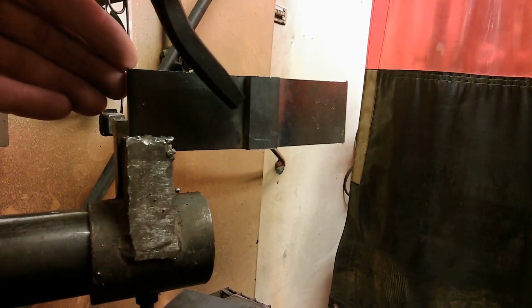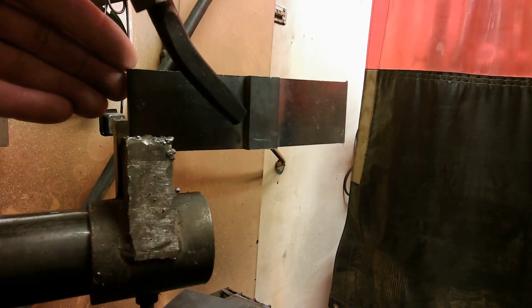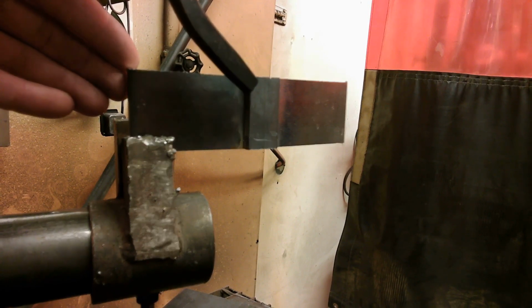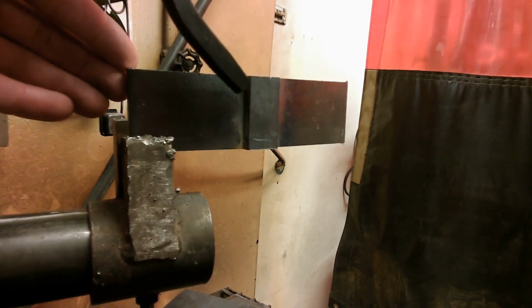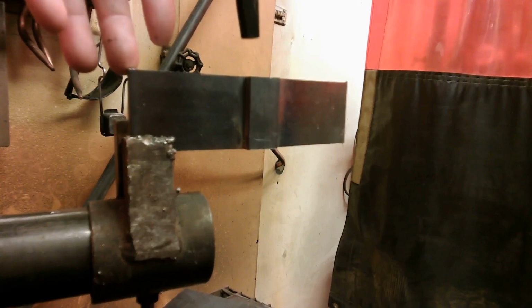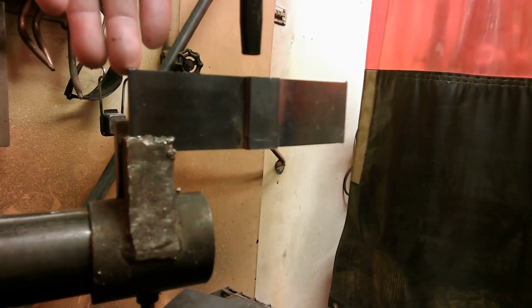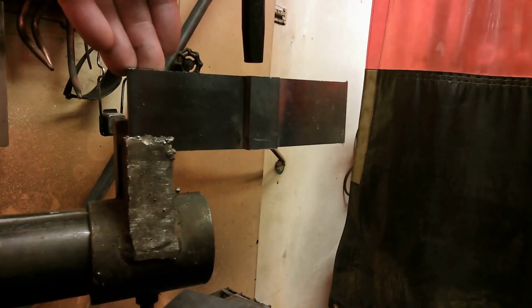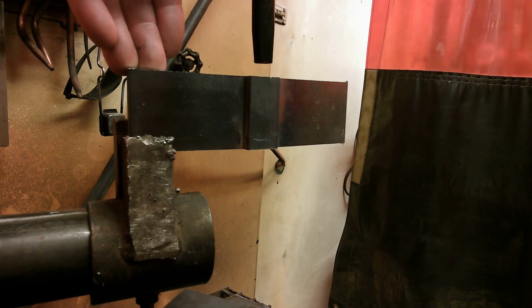Heat rises, so I want to preheat that bottom piece and I'll bring it all the way up. Kind of back and forth, get that hot. Then I'll tip my torch up and preheat that corner. It doesn't take more than about 2-3 seconds. It's on an edge. And I'll hit my cutting jet. At that point, it takes about a second or so for that stream to shoot all the way down to the bottom. And then I just brace my hand and walk that all the way across, trying not to gouge in the center portion.